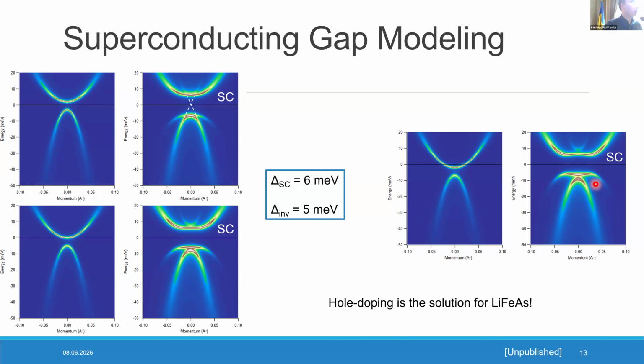Yes, thank you for the comment. That is very true. What is interesting, from my experience, is that ARPES is of course surface sensitive, but the samples are also measured in ultra high vacuum, and we even saw on many samples that when a sample is sensitive, not specifically to topology or surface states, but in general, you see it during measurements. Like in 1 hour, you already see that the surface got worse if it's very sensitive.